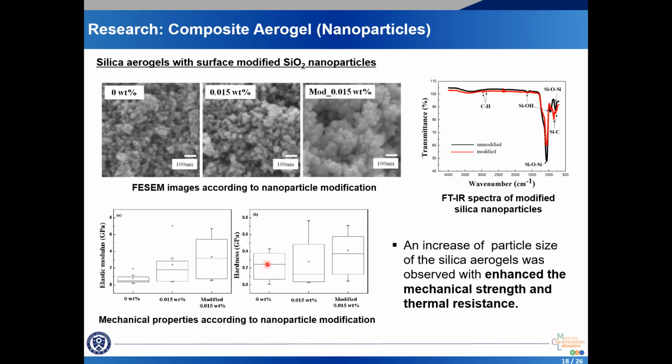An increase of particle size of the silica aerogels was observed with enhanced mechanical strength and thermal resistance. This result indicates that the introduction of silica nanoparticles with surface hydroxyl groups into silica gel is a feasible way to control the synthesis of the nanocomposite.